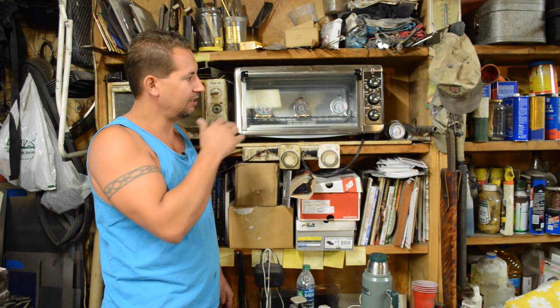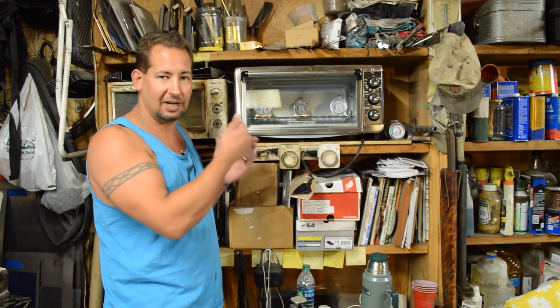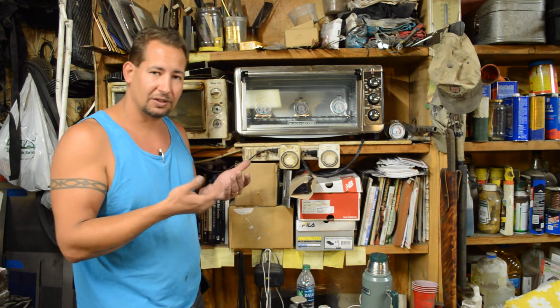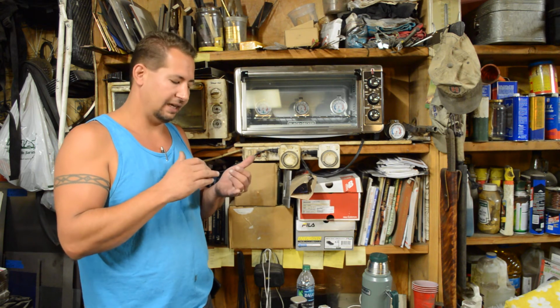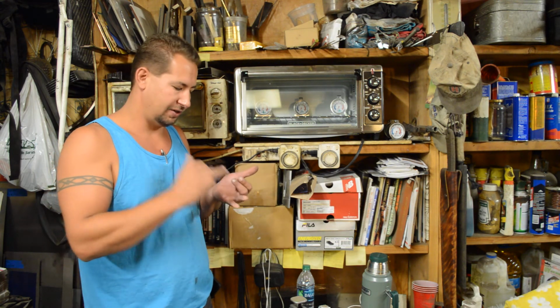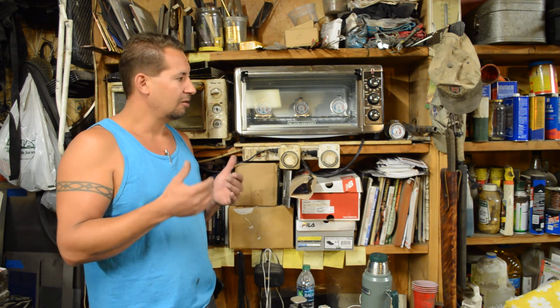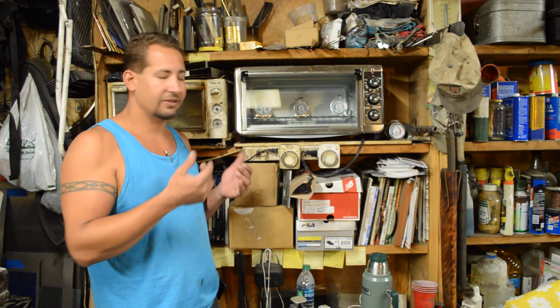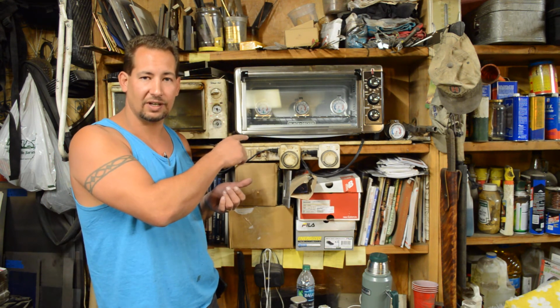So anyway, by doing that, you're using the steel to calibrate the oven. And really, when it boils down to it, you can talk about Rockwell numbers, you can talk about absolute temperatures, two guys swapping heat treat information. Well, they've got different toasters, Rockwell hardness testers can get out of calibration, apparently there's a fine art to using those things. But really, at the end of the day, the performance of the steel is the only thing that really matters. So why not use the performance of the steel to calibrate your equipment?